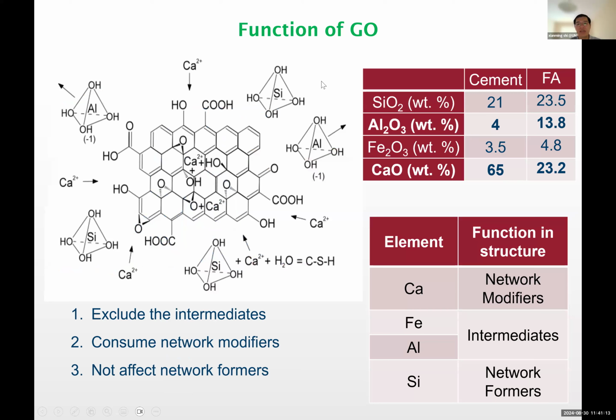So in summary, what is the function of the graphene oxide? Again, these are carbon-based nanomaterials like a platelet, but on the surface with a lot of functional groups like carboxyls, hydroxyls, and so on. So the negative charge, they exclude the intermediates. These are typically calcium cations, and they consume some of the so-called network modifiers, which are the calcium cations, but they exclude the intermediates, which are typically aluminum tetrahedrons, which are negatively charged. But the silicon tetrahedrons, most of them don't have any charge, so they're not affected.